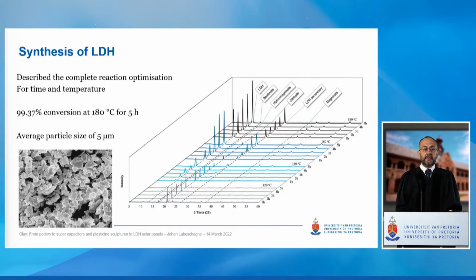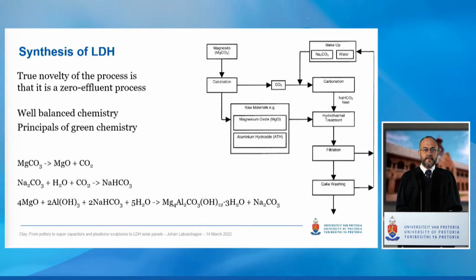And we could achieve a yield of 99.37% at 180 degrees Celsius with a 5-hour reaction time, which is quite phenomenal for a commercial product. The average particle size of the clay was 5 microns. And if you remember, that is spot on to what we have for natural clays. Here I present the process, or the flow diagram, as it was in the patent, and not the nicely drawn aesthetic one that we had in the publication.